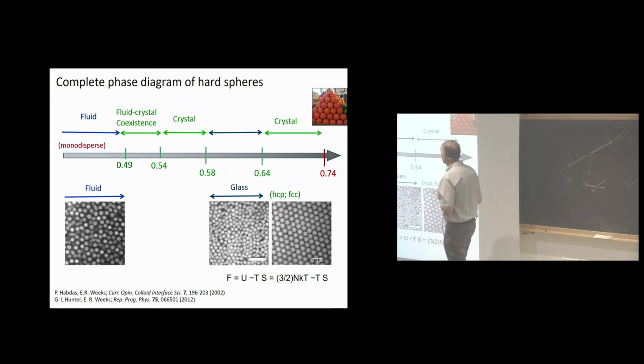you lose the crystal, and you form a glass, right? So basically the material becomes amorphous, so you might have seen that you lost the Bragg peaks, and then eventually you have again the reappearance of a crystal, and you go all the way to 0.74, which is the maximum close packing, right? So this is again a confocal microscopy image of a fluid. This is a glass, and this is clearly much more organized. Either FCC or eventually hexagonal close packing arrangement of hard spheres.